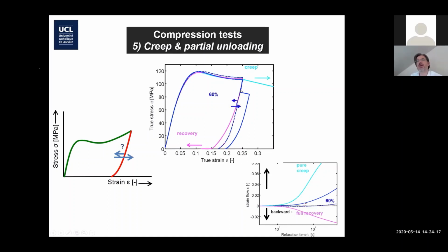And if you go down to 60%, what you have is interesting. You start with a little bit of backward creep, so a little bit of recovery, followed by forward creep. So you're not finding a stagnation point. You find a condition where the material keeps recovering a little bit, so under compressive stress, you maintain the force, and the material elongates a little bit. And then if you wait longer, it keeps deforming by positive creep. Okay?